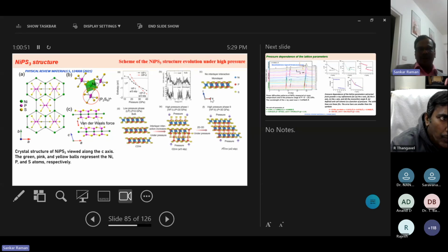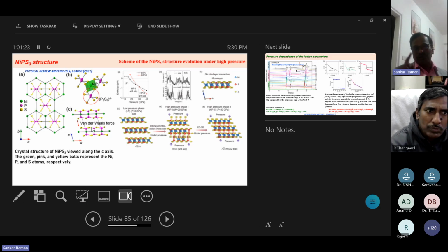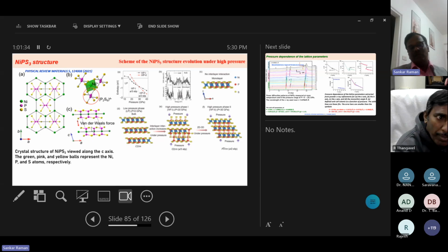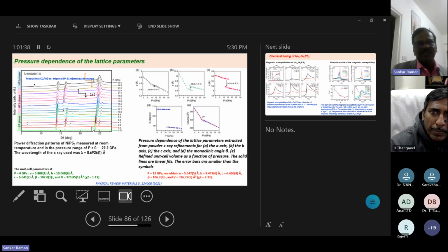Then the structure has a honeycomb lattice, and below the honeycomb lattice is coordinated with the phosphorus sulfur one. In between, you have a van der Waals force. The van der Waals force is very important. In this case, we need to check whether any phase transition occurs if we apply pressure. But when we grow the monolayer, we never see any phase transition in this monolayer film. But in the case of bulk material, because you have a van der Waals gap, we applied up to 30 GPa, and we clearly understand it moves from C2/m to C2-bar/m and P3-bar 1m after the first transition to the second transition. You can clearly see the X-ray diffraction using high pressure X-ray we did.